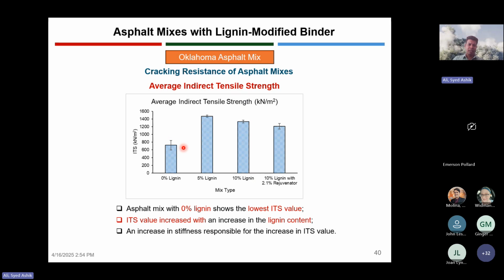We have seen that for 0% lignin, the ITS value, or the indirect tensile strength, was pretty low, but with 5% and 10%, it went up very high. And with 10% lignin with 2.1% rejuvenator, it came down a little bit with the addition of rejuvenator. But an increase in stiffness of the asphalt mix is actually responsible for the increase in the ITS value.